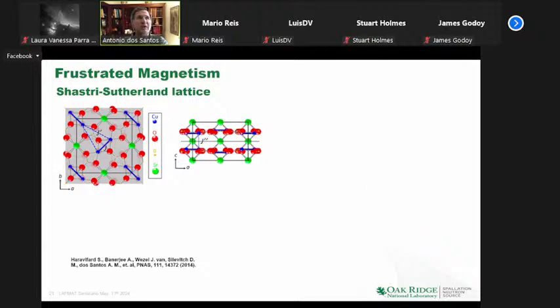The Shastry-Sutherland model of orthogonal dimers has an exchange inside a dimer and another exchange between dimers, which is symmetrical. So each dimer end couples the same way to the other dimer in this triangular fashion. It also assumes that the J double prime, the interlayer coupling, is negligible.